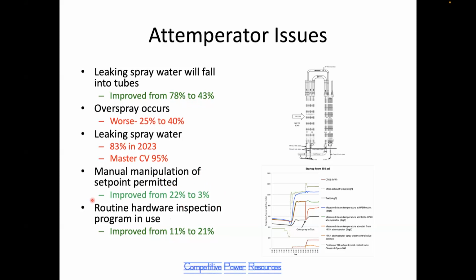All of these things we just talked about with the Attemperators, the nozzle failures, pipe cracking, part of that is because the Attemperators have a very difficult life. They're exposed to very high steam temperatures and intermittently exposed to cold water temperatures. So they are very, very heavy duty, stressed equipment. So it's important to inspect them regularly to look for these problems before they get so bad that they cause a tube failure or a piping failure.